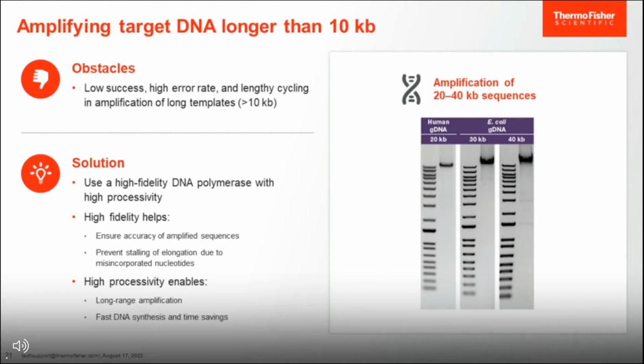It is often a challenge to amplify long DNA fragments, for example, longer than 10 kilobases. Success rate is often low, there is high error rate, and a long cycling protocol. In such situations, a high-fidelity enzyme with high processivity can simplify the workflow because the enzyme ensures low error rate and better amplification of longer fragments, while high processivity leads to shorter cycling time and also increases the success rate of the amplification overall. The gel image on the right side shows amplification of 20 kilobases from human genomic DNA and even up to 40 kilobases from E. coli genomic DNA using our high-fidelity Platinum SuperFi II DNA polymerase.